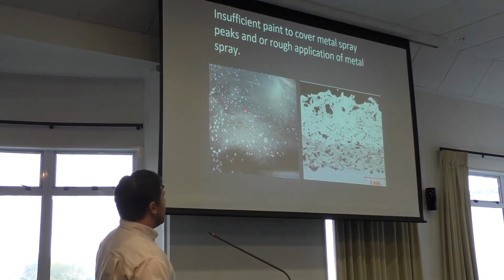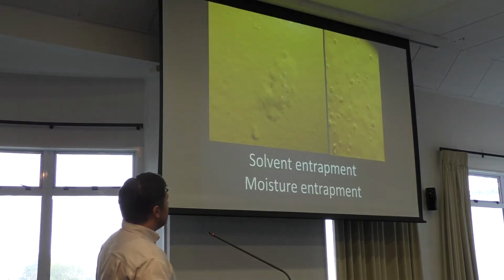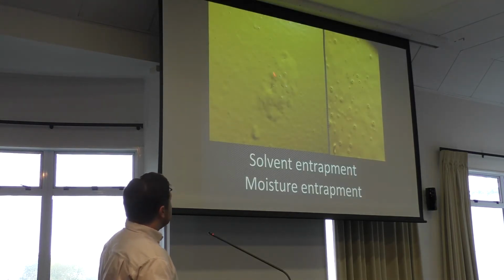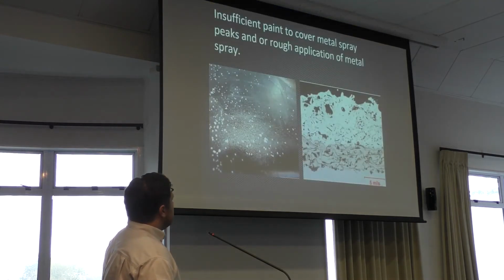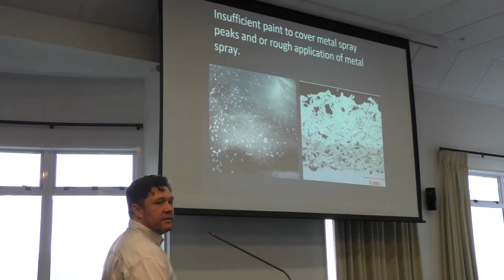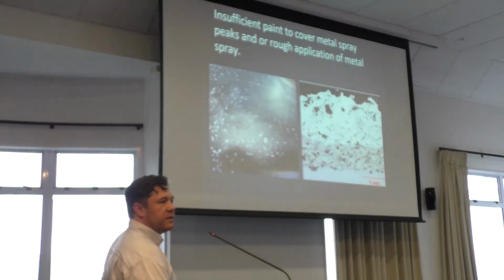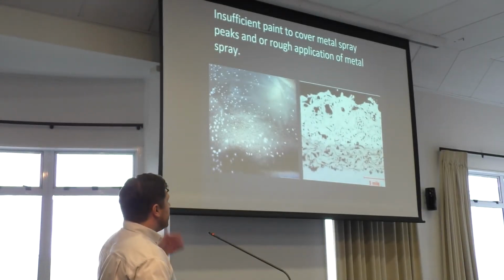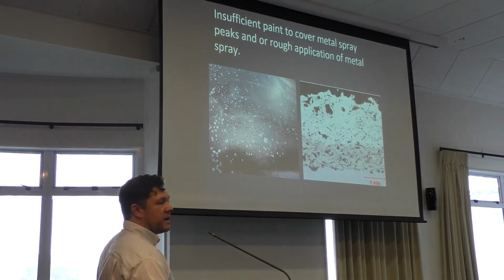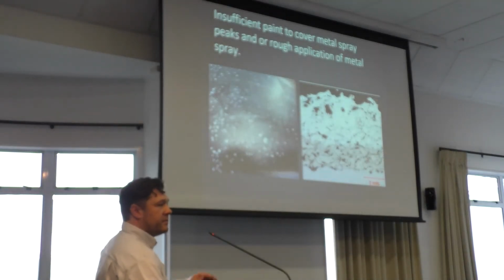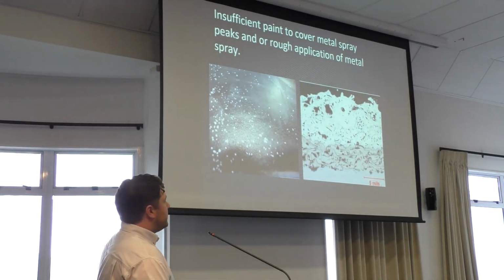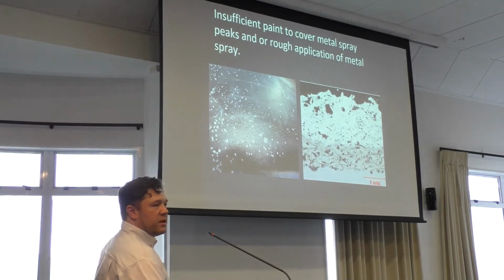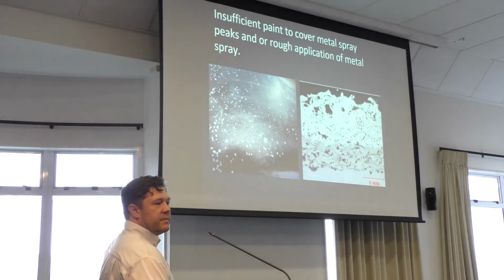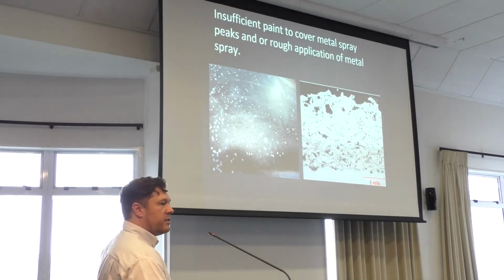You can see here how it looks, and a little bit in the one before, with the white spots coming through in areas. I mean, that's a big activation. But you can see the white spots coming through prematurely. So it's nice new paint, and there's corrosion products on top, and that's a little bit concerning for people. So in this situation, there just simply wasn't enough paint to cover that zinc, so we're getting the peaks of it activating first, and if we left that for a bit longer, it would start to look like a little volcanic pimple, if you like, of the zinc activating and the coating peeling off around it.